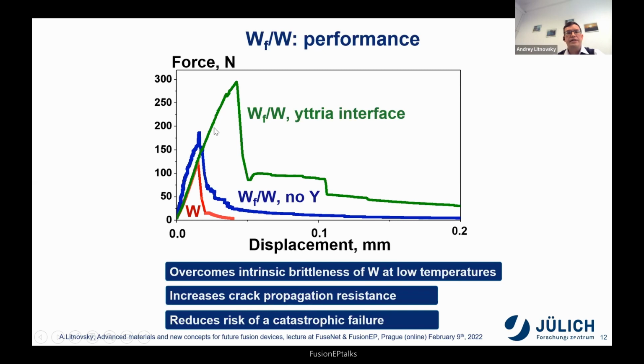So it still fights against this. And also you can see already the difference in the maximum force which is applied in order to get this crack at all in this material. Whereas with optimized tungsten-fiber-reinforced materials, you can see that the maximum force applied is already double as much.